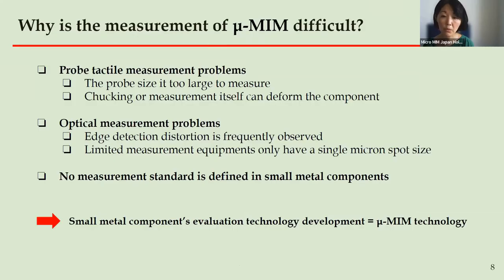Let us explain why the measurement of small components, such as these micro-MIM parts, are difficult. The tactile dimensional measurement is commonly applied for 3D structural observation. The probing ball diameters of conventional probing systems range from 0.5 to 0.2 mm, and probing balls of this size normally pose great problems. The measurement uncertainty strongly increases due in particular to elastic and plastic deformation in the probing system.